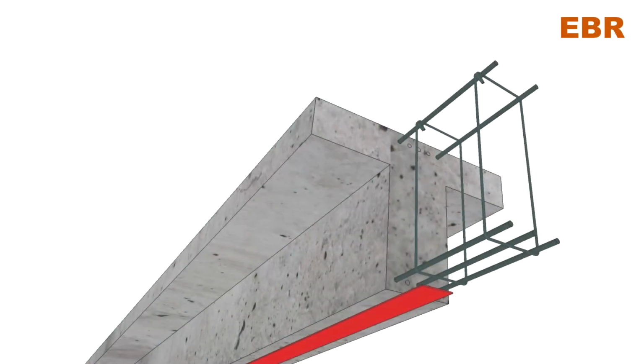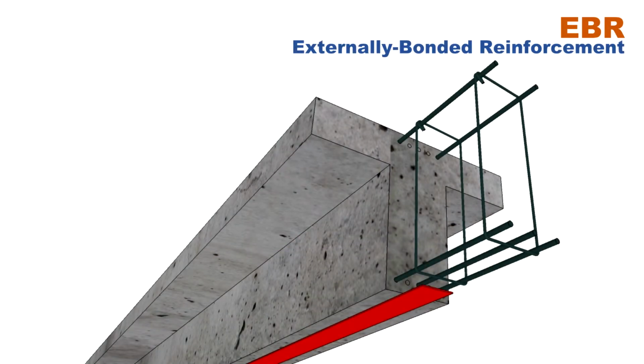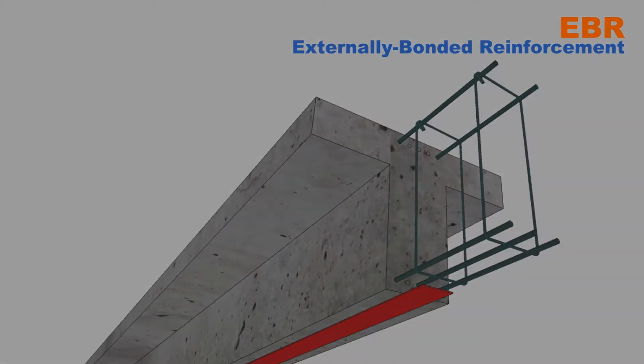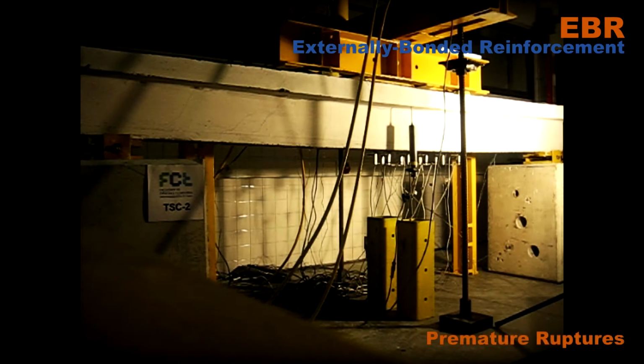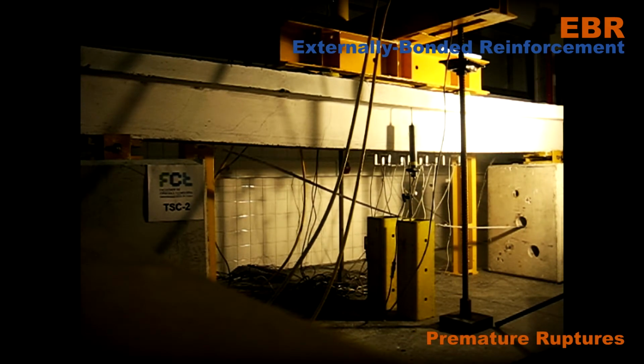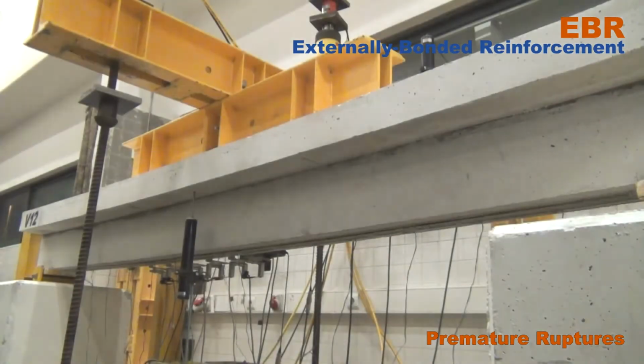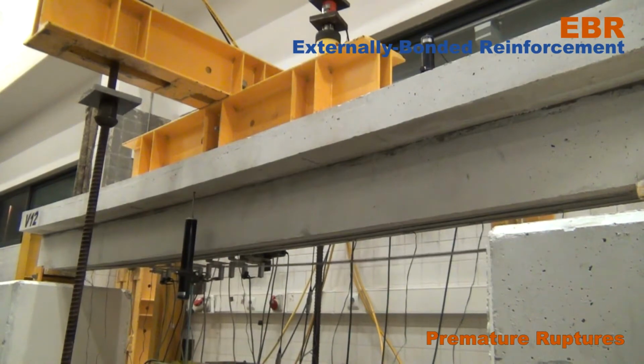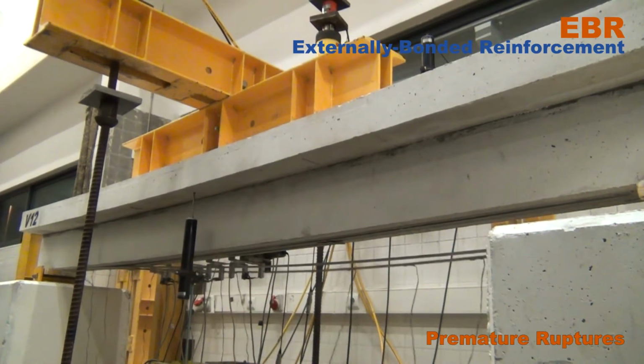In reinforced concrete beams, the EBR technique has presented bonding ruptures between the reinforcement and the concrete surface. With the EBR technique, the rupture of the test occurred due to the bonding between the reinforcement and the concrete surface, regardless of the strengthening material, be it stainless steel or FRP composites.